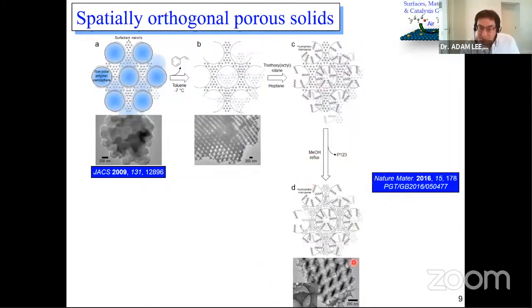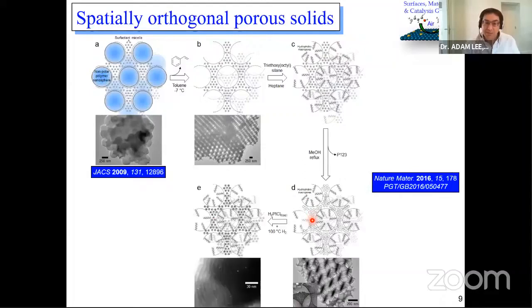So we have large macropores, you can see here, a few hundred nanometers, and we have mesopores that are well defined as well, and they're empty. But the surface chemistry is different. The macropores are hydrophobic. The small pores you can see here are hydrophilic. And that means when we put a metal precursor in, they will go to different locations.